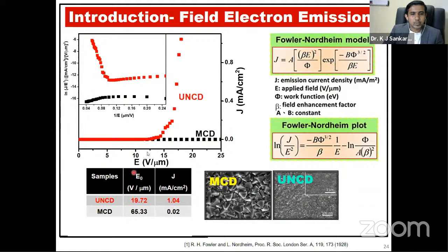But UNCD has a very low turn-on field and also a high current density of nearly 1.04 milliamp per centimeter square. But MCD has a very low current density. So we have achieved that UNCD is much better than MCD in field electron emission. To know the reason why UNCD is better than MCD, we need to characterize the material.